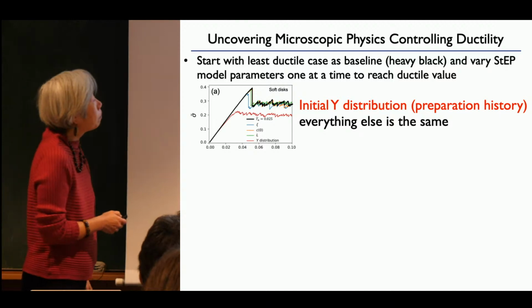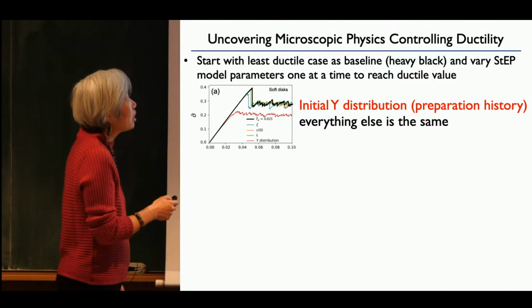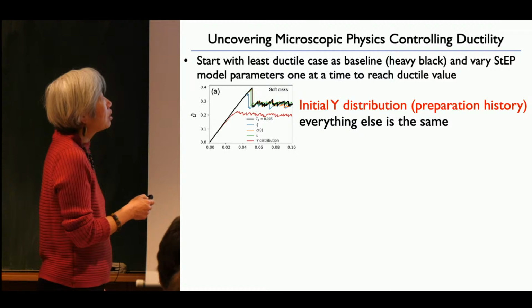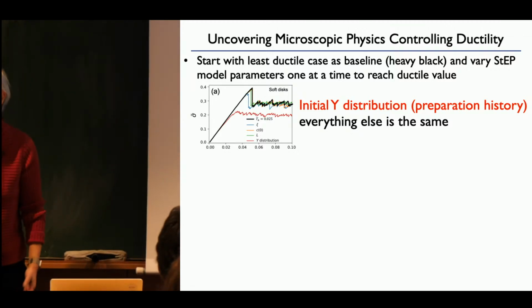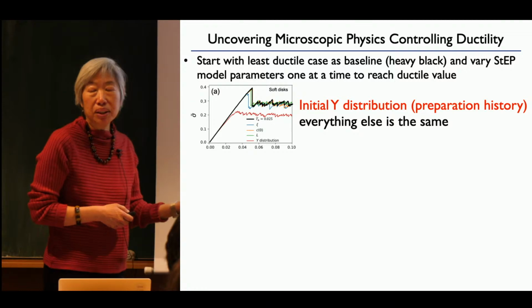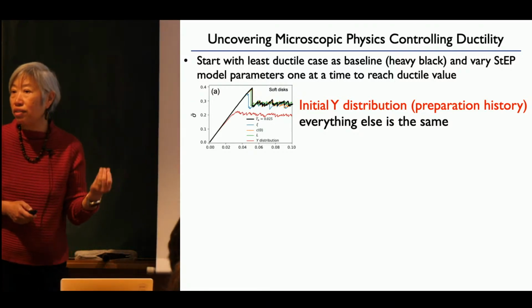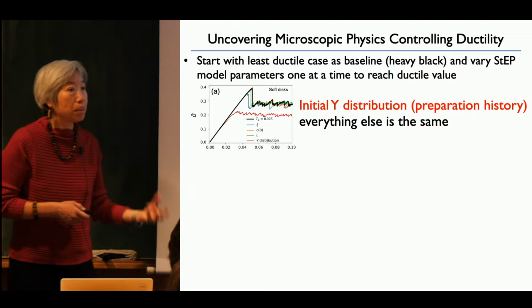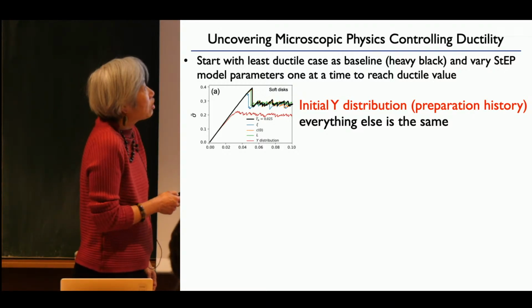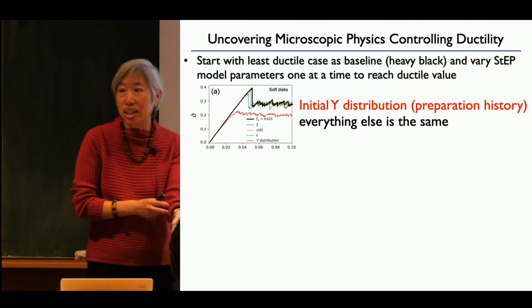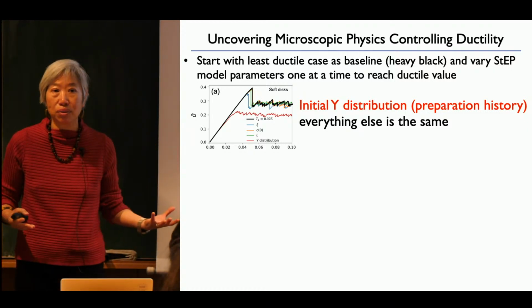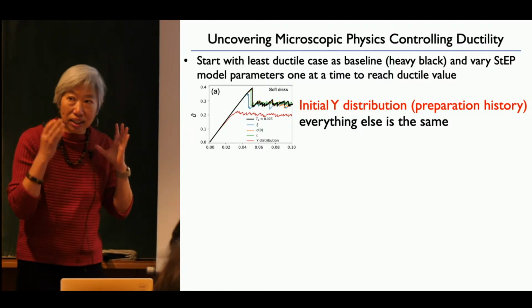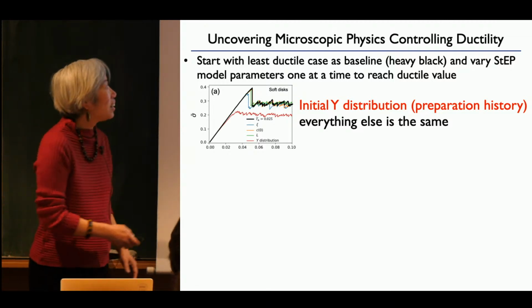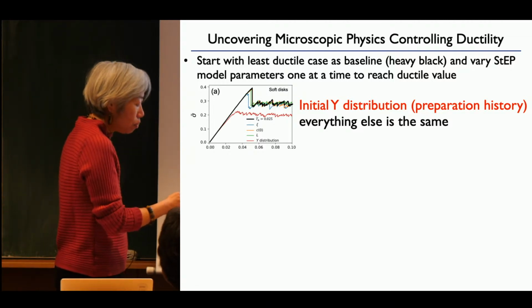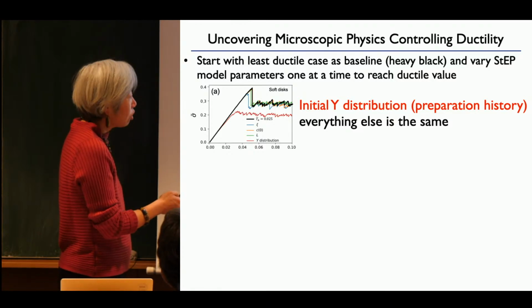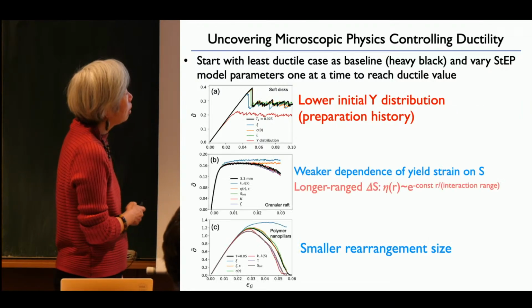And in the case of soft disks, I told you nothing else changed except for one thing, and that was the distribution of Y, which was very different in the 2 cases. So it's simply the initial distribution of the yield stress which changed this behavior. And that's, of course, exactly what it should be, because what changed in that system was the preparation history. Everything else was the same. So this indeed gave us a reasonable result, that it's just the initial distribution of the structural proxy for yield stress that made the difference.